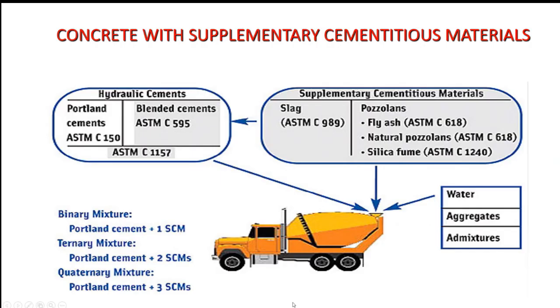Adding supplementary cementitious material of pozzolanic action directly to the concrete mix instead of part of the Portland cement contributes to reducing the cost of concrete, increasing the strength in the subsequent period of hardening, and increasing durability. In this case, replacing each kilogram of clinker in concrete with additional cementitious materials allows reducing CO2 emission by 0.61 kilogram.